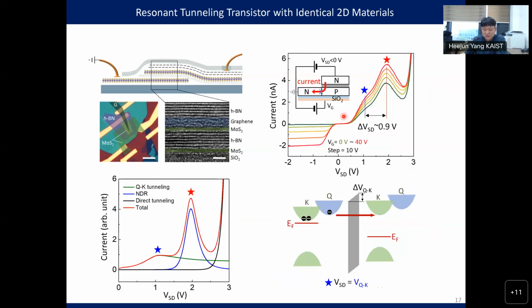Of course, there are some technical things. For example, can we shift the Fermi level freely in the band gap, which is not possible for N-type silicon and P-type silicon. We have some Fermi level pinning. But here we have a nice property of 2D materials. We have no dangling bonds. We can freely shift the Fermi levels. So this is one evidence. If we look at the whole voltage range, we have some current saturation because we have reverse direction. But I will not go deeply here. So we have this momentum-driven transport, and then we can make this Fermi level shift inside the 2D material band gap.